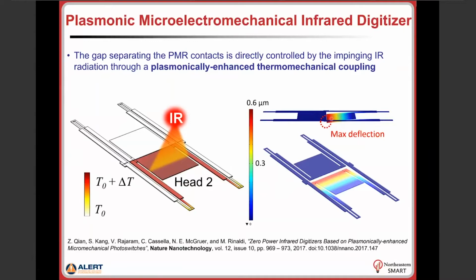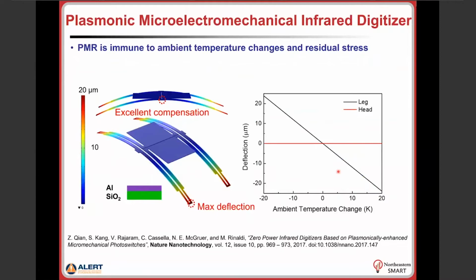So in other words, the air gap that separates the two contacts is really controlled by the impinging infrared radiation through a plasmonically enhanced thermomechanical coupling, right? So despite the fact that this structure is so sensitive to infrared-induced temperature increase, the structure is instead completely immune to ambient temperature variation and residual stress that we might have in the thin film materials that are used to build these microcantilever structures. And that is really due to the use of these outer pair of thermally sensitive legs, right? That substantially perform a sort of in situ compensation mechanism for ambient temperature variation.